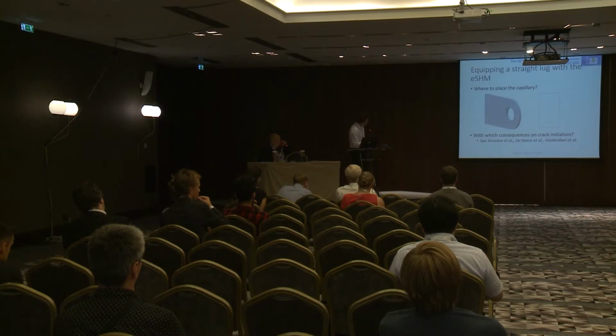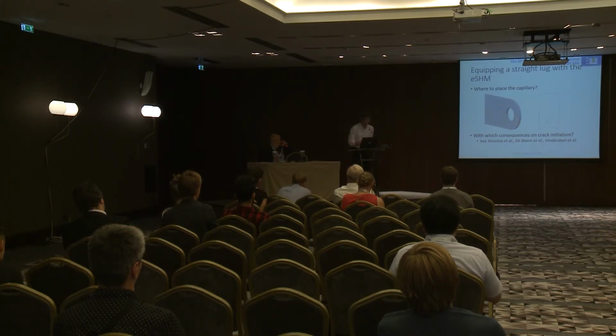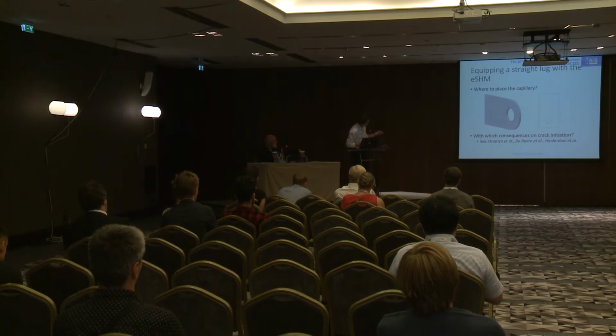What they have noticed is that if you place the capillary too close to the initiation region, you have a risk that the crack would initiate at the capillary itself, because there are two effects. First of all, you introduce a stress concentration, so you risk that the stress around your capillary is higher than the stress in your critical regions, which is of course not interesting. Furthermore, here I've drawn the capillary perfectly smooth, but since we do additive manufacturing, you have a bit of roughness inside that capillary. So you effectively have a risk